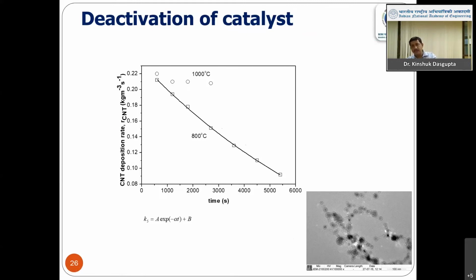If there is more supply, or if the active surface of the catalyst reduces, then there is relatively more supply of carbon molecules than required. So what will happen? There will be soot formation or an amorphous carbon coating on the catalyst particle, which cannot further catalyze the growth of the carbon nanotube. So this deactivation we could also model with an equation, and we could predict up to what time you should synthesize the carbon nanotube.